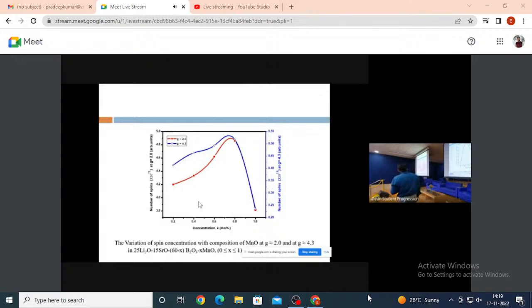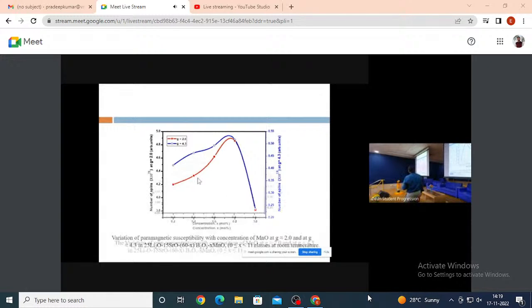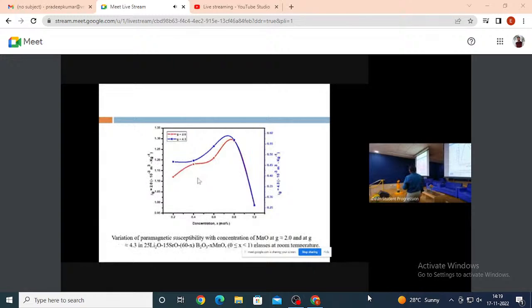From this graph, I can say that the number of spins participating in the resonance increases up to 0.8 mole percent of MnO. Later, the number of spins decreases. It also shows that up to 0.8 mole percent of MnO, the Mn2+ ions increase at the expense of Mn3+ ions. This graph shows the paramagnetic susceptibility. Here also, up to 0.8 mole percent the susceptibility is increasing, and later it is decreasing.